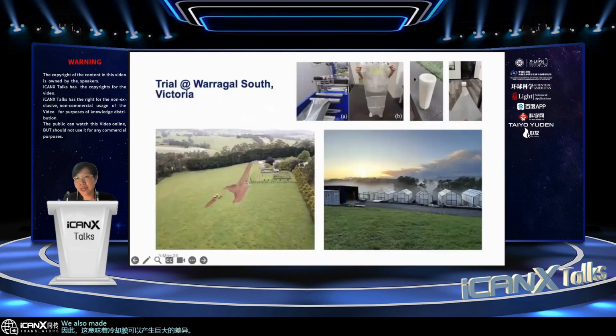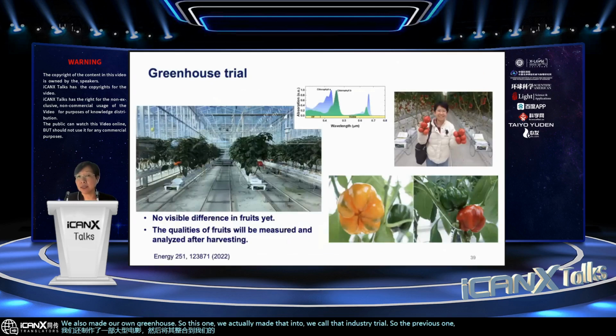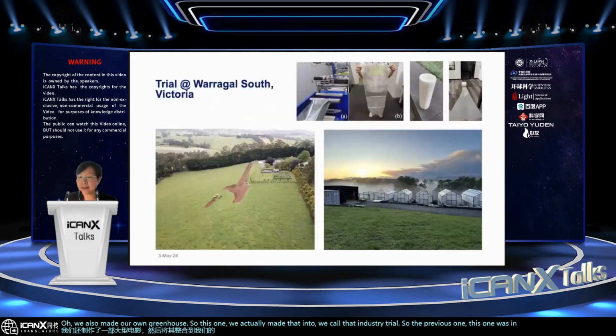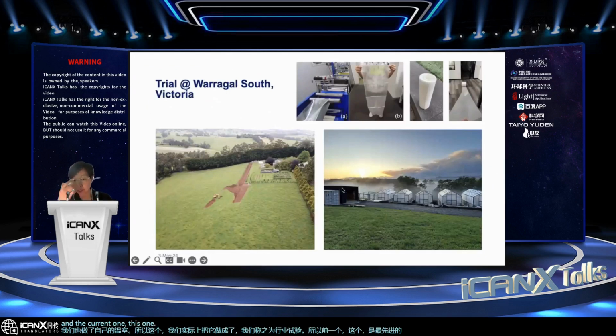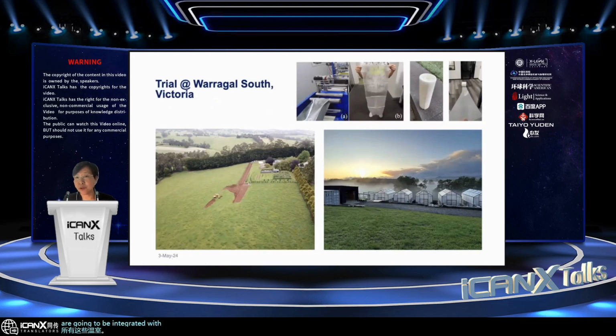We also made a large-scale film and integrated that into our own greenhouse. We call this an industry trial. The previous one was state-of-the-art research-based, and the current one I show is for the industry trial in Victoria. All these greenhouses are going to be integrated with this cooling film. And we found the plant yield has also changed. Most of them are positive changes. This is also very good news for us.